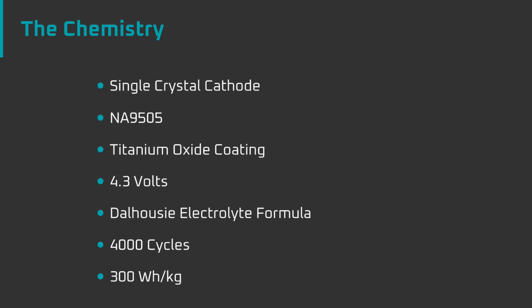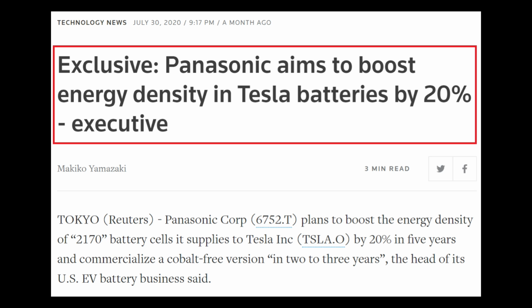I also advised this chemistry would increase energy density by up to 20% to hit 300 watt-hours per kilogram of specific energy. I view Panasonic's recent statement as confirmation that my estimates were correct here. They indicated a 20% energy density improvement by 2025. That would increase their current 247 watt-hours per kilogram up to about 296 watt-hours per kilogram.